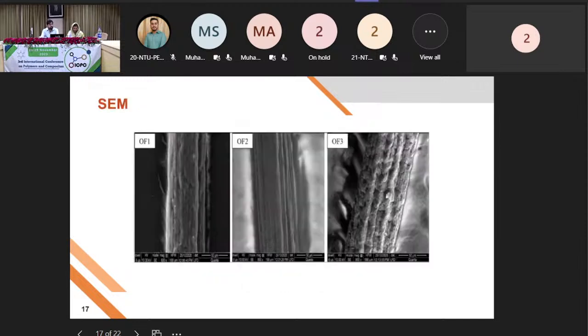The SEM analysis shows the surface topology of the developed fibers, which are quite rough and have linear lines. This shows that during coagulation, the material becomes dried and solidified at a stage where it becomes shrunk.